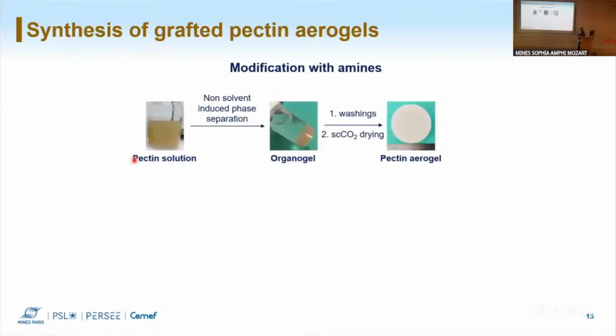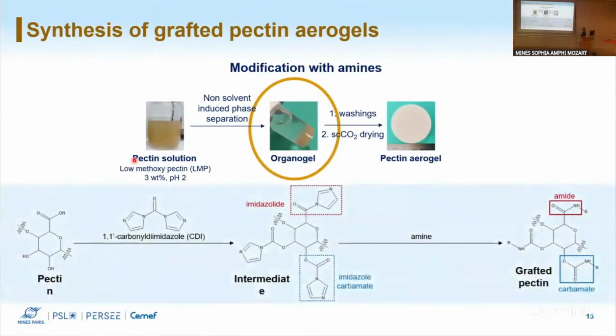In the general scheme now, we've worked with the organogel. So we are in heterogeneous reaction, and we used low methoxy pectin at 3 weight % and pH 2 from the initial aqueous solution. Here we can see the reaction that is performed. The first step reaction was carbonyldiimidazole to activate the functional groups of pectin. And the second step, we add an amine.